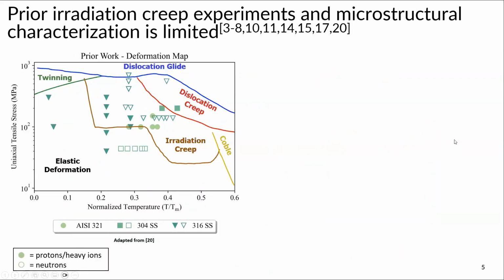So during my literature survey, I found all of the prior work done on the 300 series of stainless steels. So you have 321, 304, and 316 stainless steel. And then I superimposed them onto that deformation map that I basically redid in Python. And so the filled markers are protons, so hydrogen ions, or heavy ions. And then the empty markers are neutrons. So it's a good smattering of those.